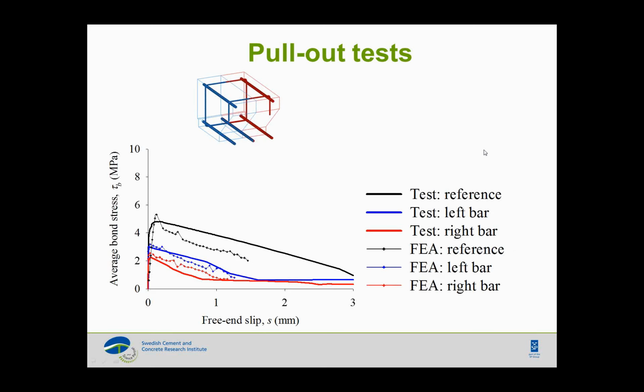Now moving into the pull-out tests phase. Now we are looking at the average bond stress versus free-end slip. So we pull out each of these reinforcements, we measure the slip on the back, and then we measure the force in front, and we show here bond stress versus free-end slip. Now looking at the non-corroded case, from experiment and from analysis, and then for the corroded reinforcement, this is for the middle bar, and then this is for the corner bar. So we have quite good agreement between what we can estimate by 3D analysis and what we see in the experiments.